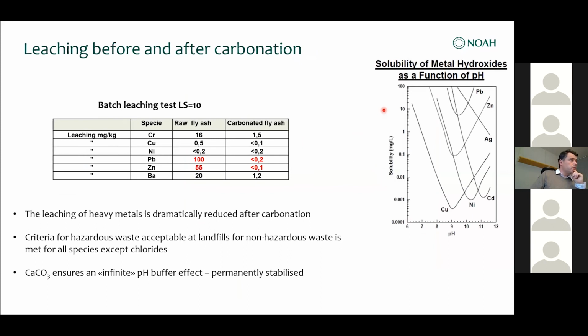Just to give you some numbers on leaching. I've selected some species for fly ash, which we believe is important. This is raw fly ash before treatment. As you can see, lead and zinc are over the limit for hazardous waste disposal. Sometimes it's much higher. But after carbonation, we see that the levels are very low; we are down to inert material or inert waste. So the leaching is reduced dramatically after carbonation if you do it correctly.